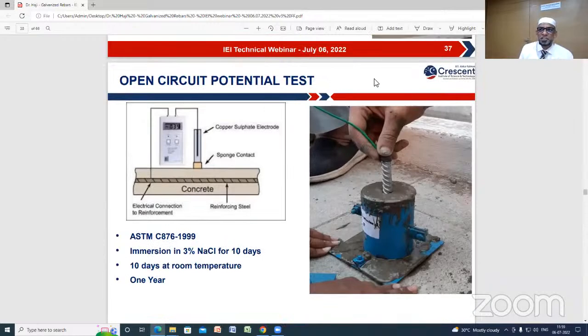Another important test, which might interest civil engineering students, is the open circuit potential test. In existing structures, we can qualitatively assess the corrosion rate of the rebar by using this half cell potential technique. In this test, we take a lead from the rebar and, using a standard electrode, we can measure the potential. Based on the potential development, we can say whether the rebar inside the concrete is under severe corrosion condition or not. We conducted this test in our laboratory. We made specimens of size like this. We varied the cover distance from 25 to 50 mm. The specimens were immersed in chloride solution for 10 days and then kept in drying conditions for 10 days, to accelerate the corrosion conditions.